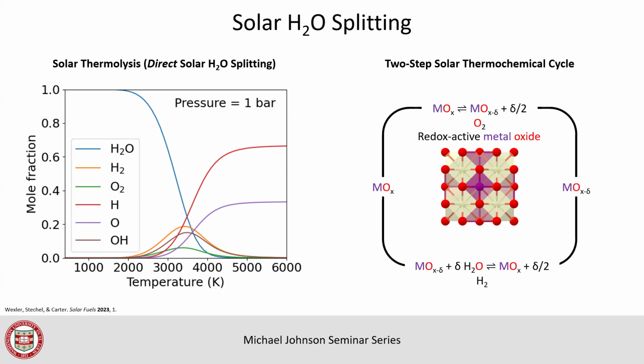The alternative, however, to splitting water molecules that are just in the air is to use a material that can act as a template for where that process occurs. Consider this two-step cycle, and you start out with MOx. MOx is my rock. It's a metal and an oxygen, and x just means there's some amount of oxygen compared to the metal, the ratio. What happens if I heat it up? When I heat this material up, it tends to release some of its oxygen. So you end up with MOx minus delta, where delta is the amount of oxygen that got lost, that went off into the atmosphere.